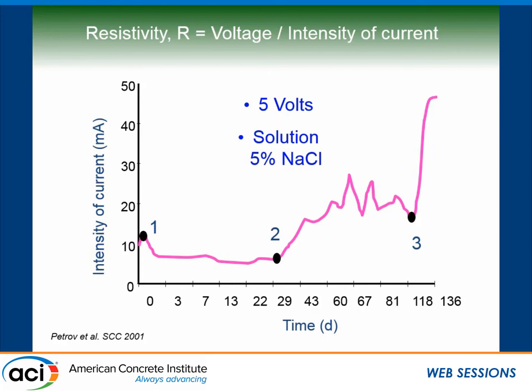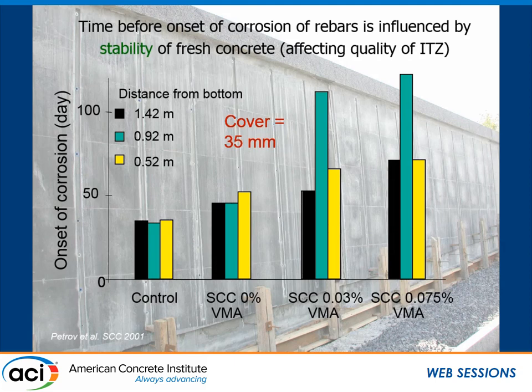So surface settlement, here we're showing it for one set of rebars, 35 millimeter cover. And then you have the control without VMA. The SCC, well, this is vibrated concrete. The SCC without VMA, the 0.03 percent viscosity enhancing agent, and the 0.075. So more settlement, high settlement, medium settlement, low settlement. And what you could see if you compare, this is the distance from the bottom. So if you compare, for example, the one near the top, 1.42 meter, you see that the onset of corrosion here is about 45 days, a little bit more. With less surface settlement, it's even higher.